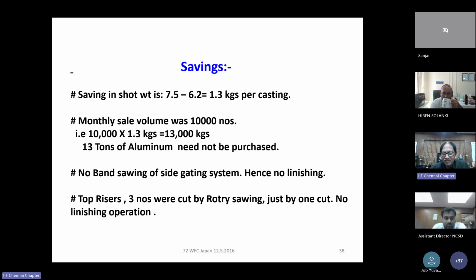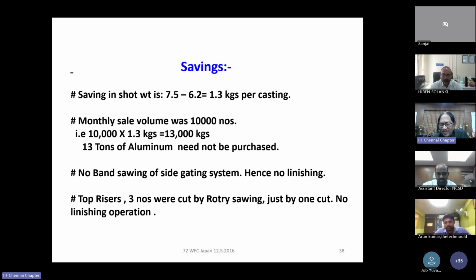No bandsawing is required. In the earlier one, the side risers had to be cut by sawing and then filed and finished. That work is not there. And also, the top 3 risers were cut by one single cut by a rotary saw. There is no bandsawing at all. Pour and cut and send it. Anything cut by rotary saw does not require finishing or grinding operations to make it even. So the casting, pouring, and one cut just by rotary saw, everything is ready for filing and dispatch.